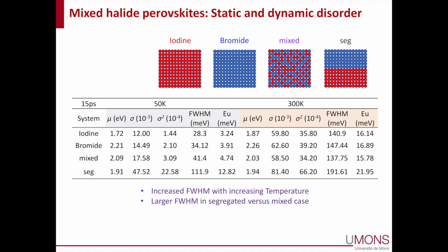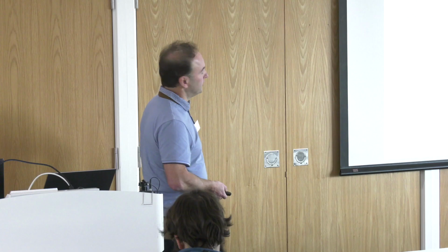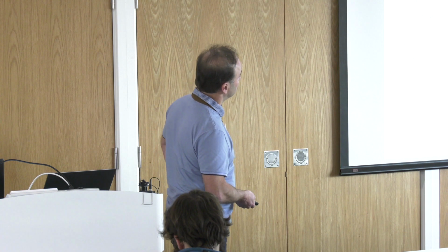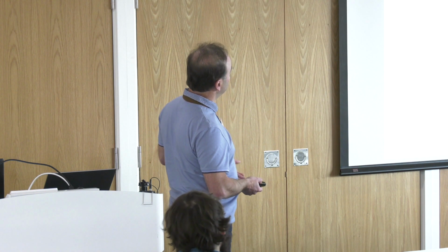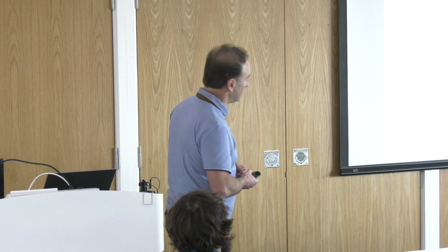And at least if you go to the mixed case, if you focus here on this column, there's not a big difference if you compare the mixed phase to the iodine or bromine pure phase. And the difference only shows up in a case where you get segregation. And we can discuss the origin of that later on if you wish. But essentially, the effect of going from the pure to the mixed case is not that dramatic on the Urbach energy.